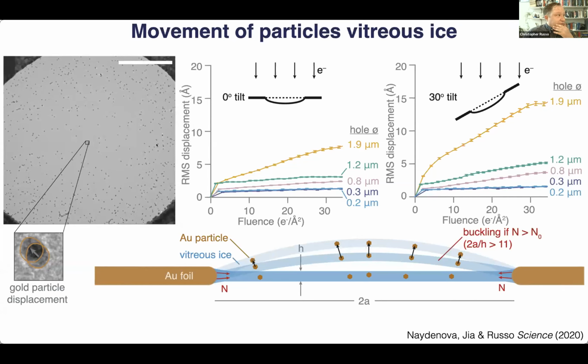So this is interesting, of course, because this means there's some real physics going on here. And this is true. You can exaggerate the effect by tilting the specimen to 30 degrees, because most of the movement that we see is actually in plane, and it's due to buckling. And so what this suggested is that there was actually a buckling phenomenon involved in the creation of these movements that we were seeing.